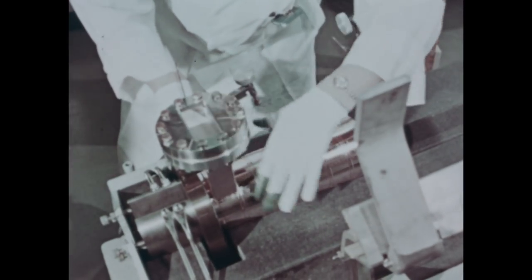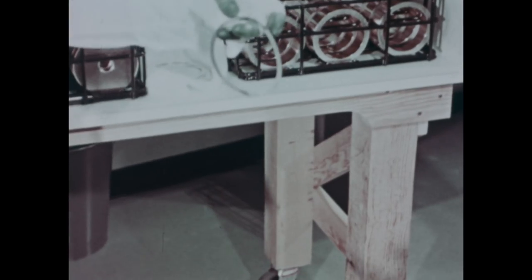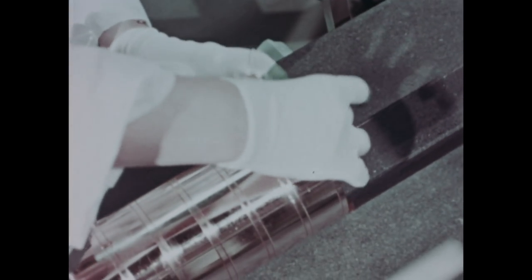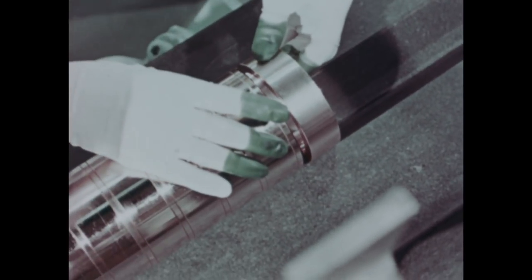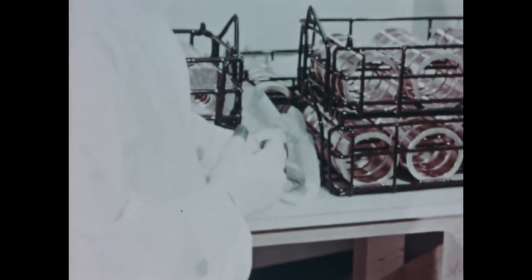After alignment, cylinders and disks are stacked above the coupler in numerical order. A shim of silver-copper brazing alloy one-thousandth of an inch thick is placed between each part. This alloy will melt at approximately 783 degrees centigrade, brazing the individual parts into a ten-foot unit.